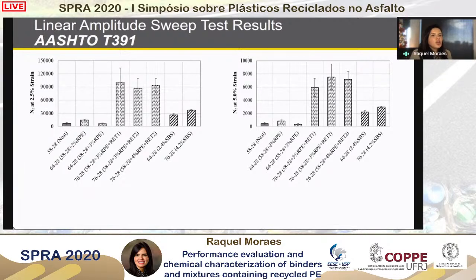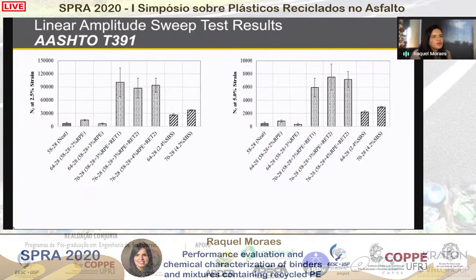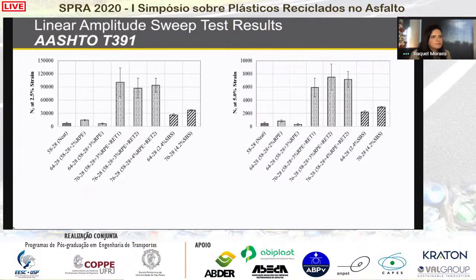However, when the terpolymer was used as compatibilizer of the recycled plastic, we see an increase in the number of cycles to failure of the blend modified with the plastics. And when comparing the 70-28 binder, that is the SBS modified binder, and the one containing the 3% of the recycled plastics plus the terpolymer, we can also see that we outperform the SBS modified binder.